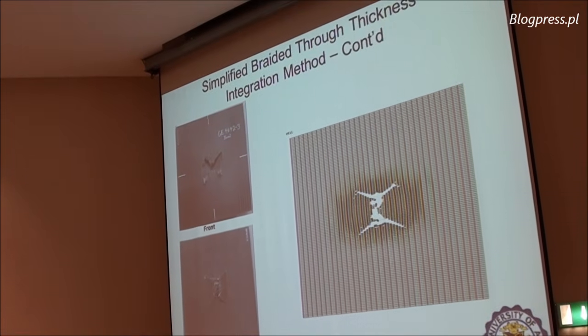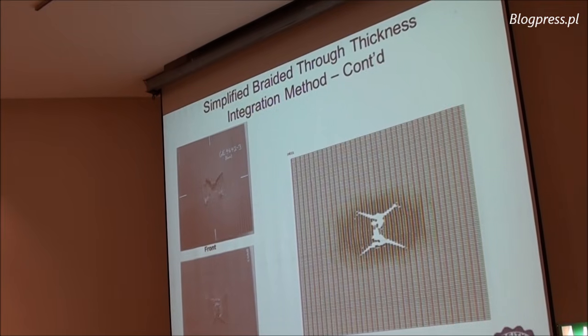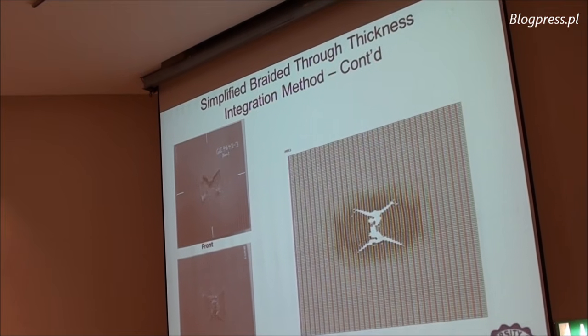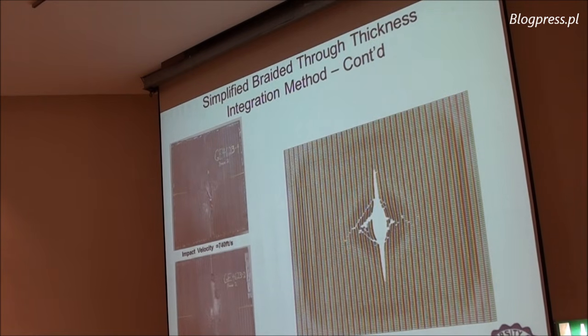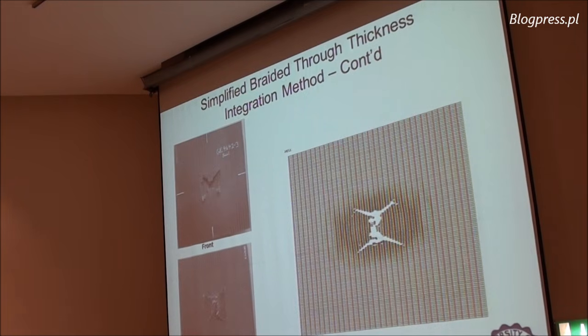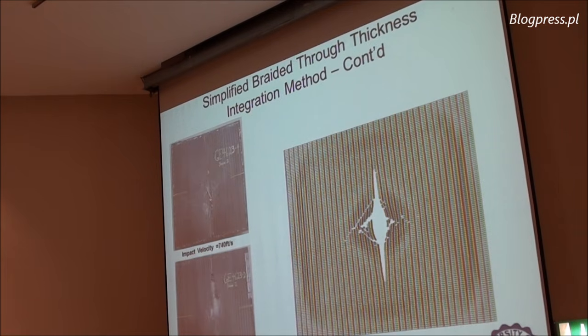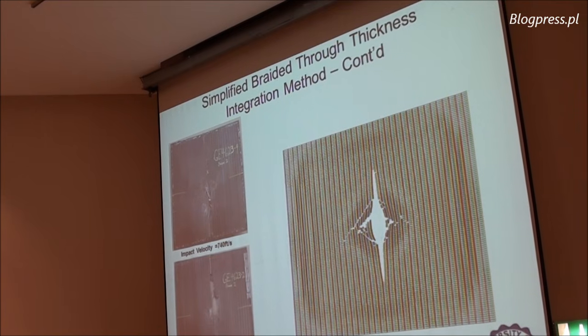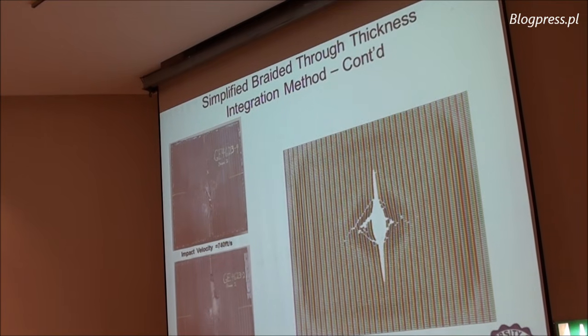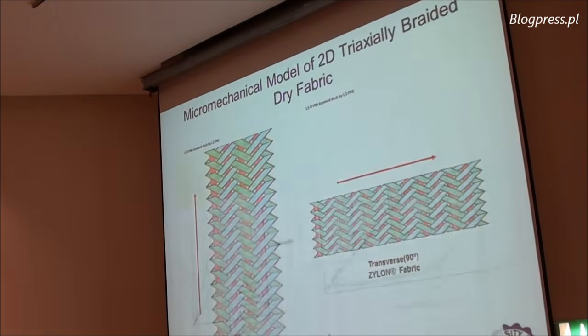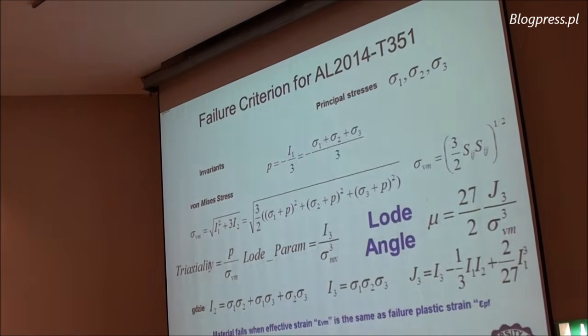Once we can get the results not only for the deformation, this is experiment, this is simulation, but also for the shape of failure, then we are very happy, and we can start making changes to the orientation or architecture of the composite. And over here we have plus minus 60, and we have the so-called butterfly shape of the damage. Here we change to plus minus 45, and completely different shape of the damage, which was predicted first and then tested, and indeed it was confirmed that the damage is like that.